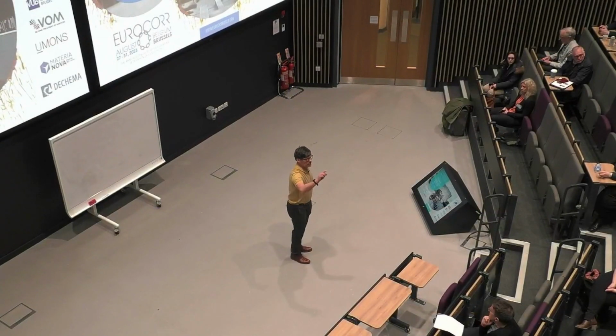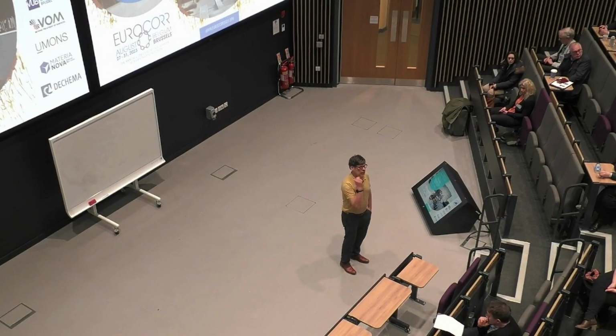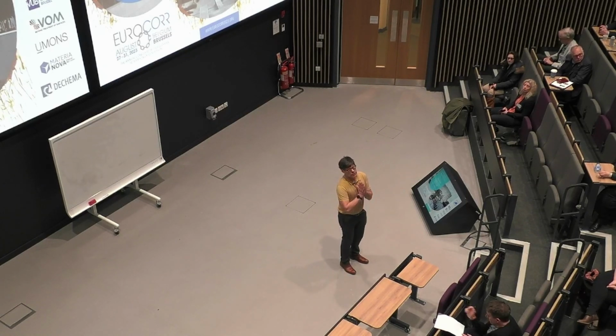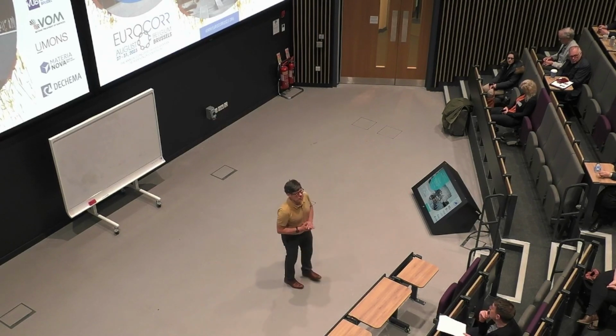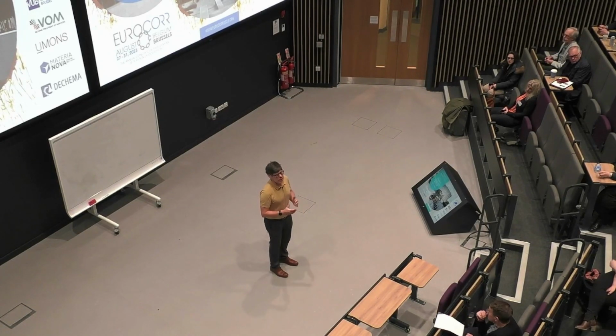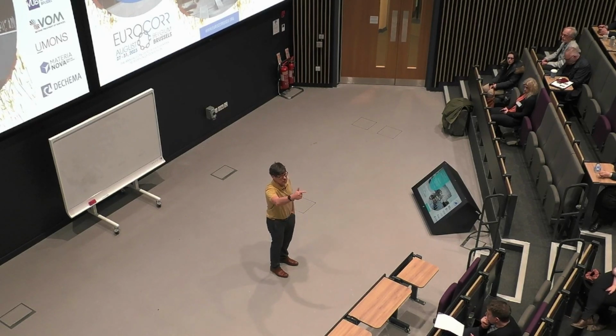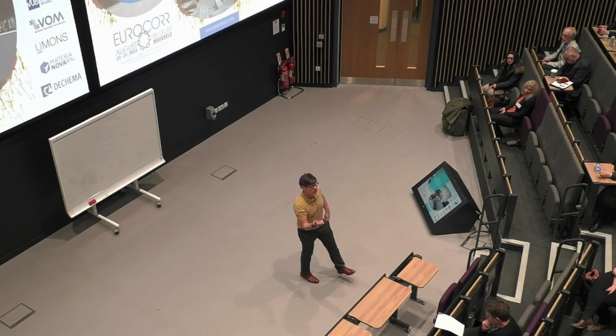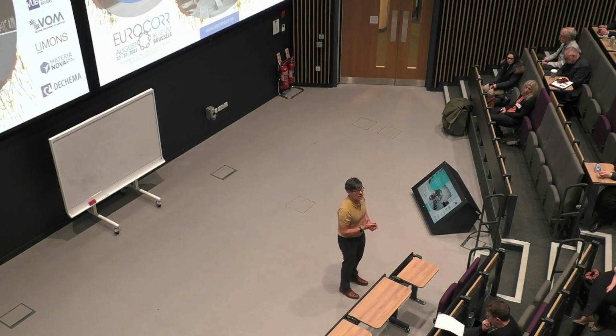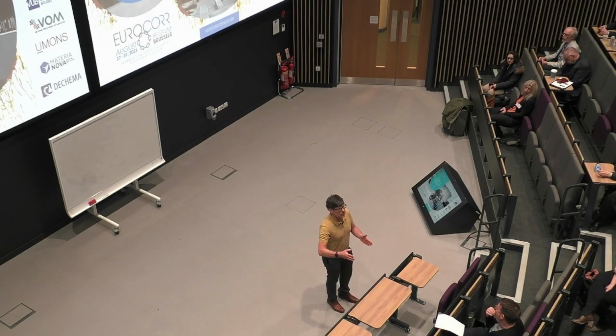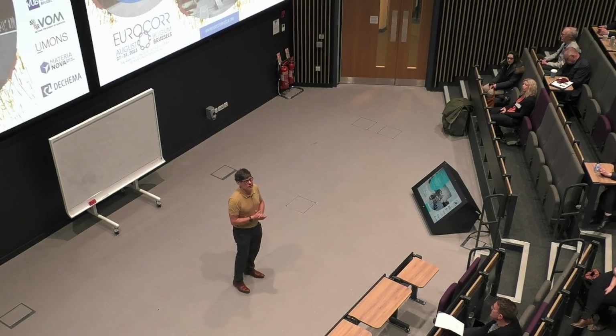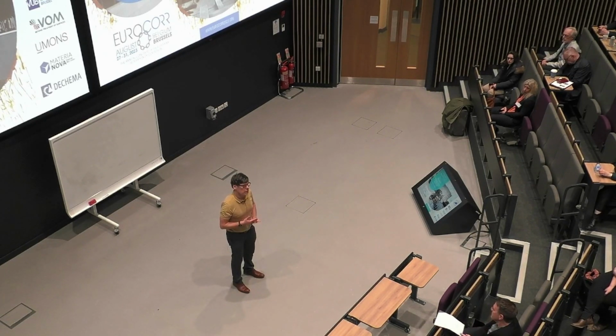Now, at the moment, the finite element modeling, and I think later you have a very good speaker this afternoon. In fact, the finite element modeling is limited to the continuous equations, the continuous theory. So the moment that you go to very small dimensions, you are running into problems. For example, one of the always discussed questions is whether you can also model initiation of pitting, the first pits that you form. At that moment, you go to dimensions which can no longer be predicted by finite element modeling. And I think for that, you need an overlap between the type of modeling that is done by DFT and the finite element modeling. So we don't take into consideration roughness parameters, or crystal orientations or other aspects, yes.